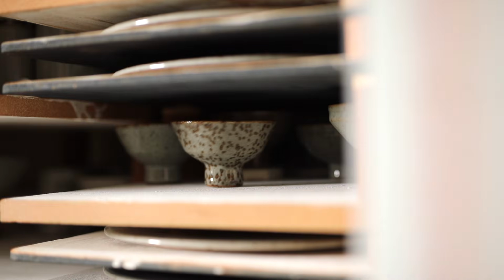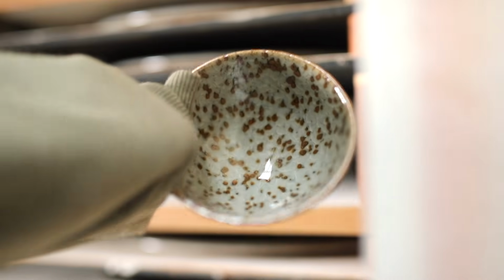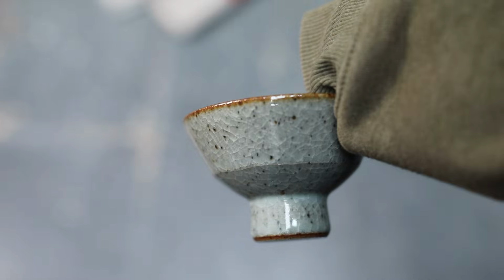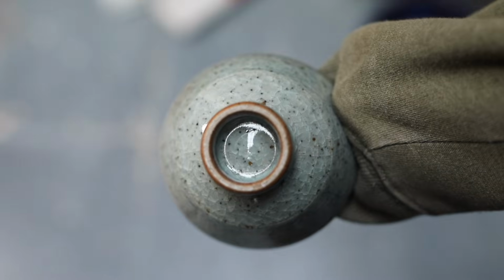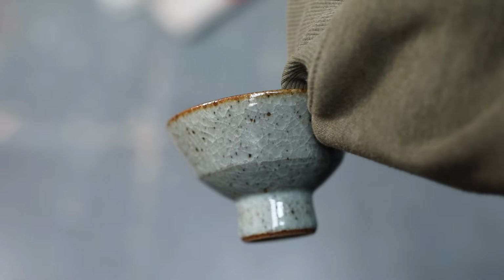Starting off with the slightly more coarse tourmaline, which did sort of what I expected. It's created a highly flecked, dotted surface, as the iron contained has turned into these little molten pools of metal. Next up is the very fine tourmaline, which by all accounts has done practically nothing. The pot appears to be slightly more speckled, but it's not very noticeable.